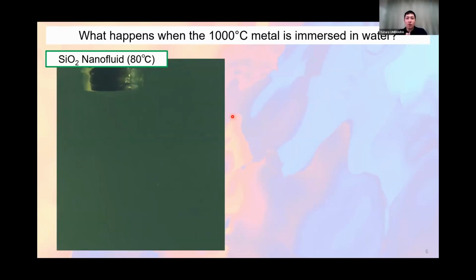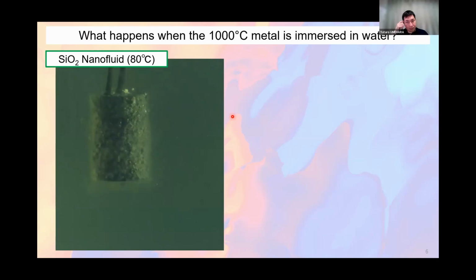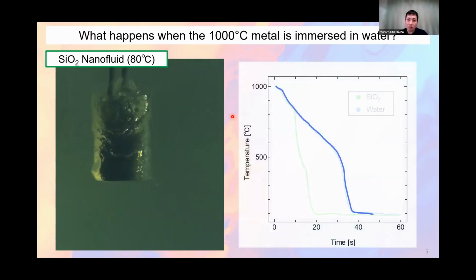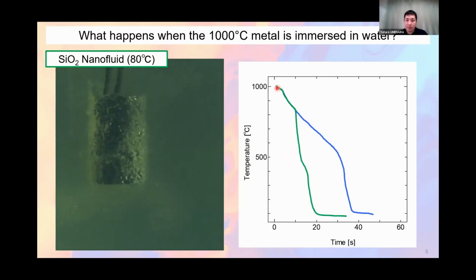So the next video focuses on the quenching phenomena in a silica nanofluid. When a 1000-degree stainless steel rod is immersed in the silica nanofluid, the initial condition is film boiling. It's almost the same as the water case, and the vapor film covers the surface. But after that, suddenly the vapor film collapses to one point, and then small bubbles are generated from the outer surface. So the cooling curve is like this, a film boiling condition, and then suddenly